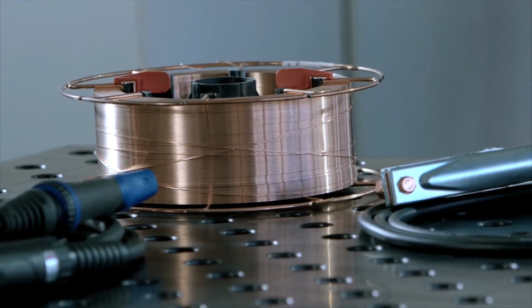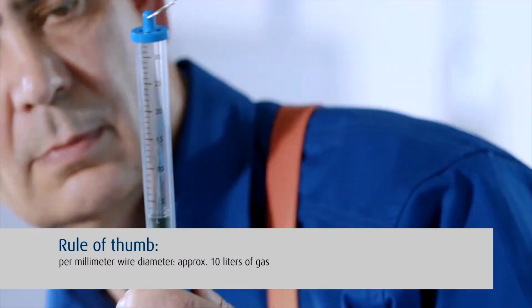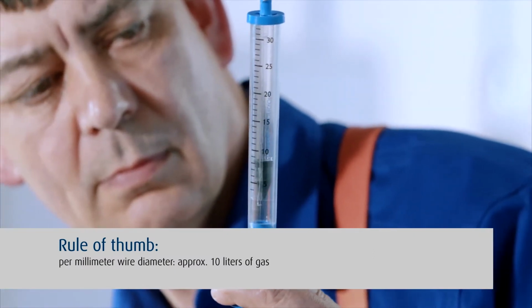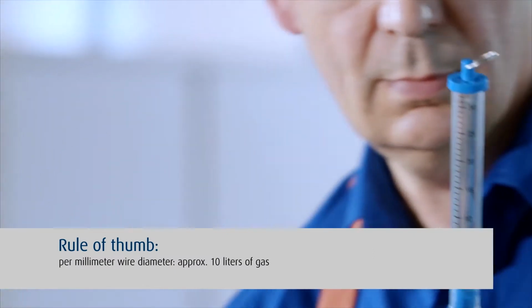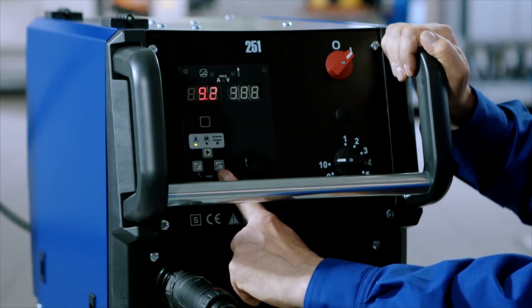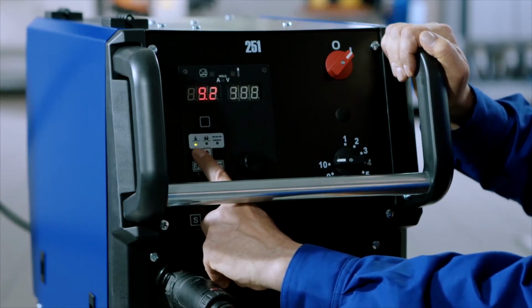The gas flow is based on the diameter of the wire. In the case of mild steel, you will require approximately 10 liters of gas for each millimeter of wire diameter, or 1 cubic foot for 0.1 inches.